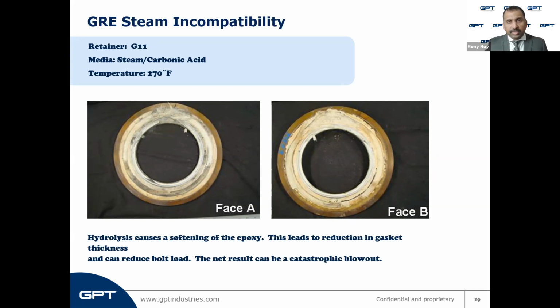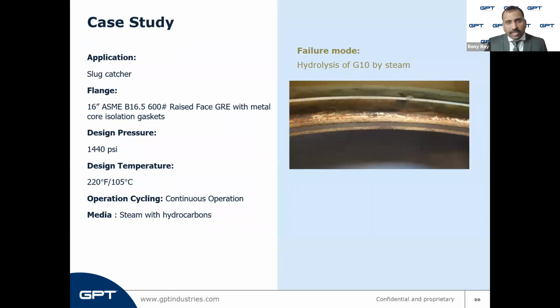And this can be seen from the two images. G11 is rated at 200 degrees Celsius. So the 270 degrees Fahrenheit should not have been a factor, but the softening of the gasket due to the steam introduction and the volume loss led to a blowout, which is a real danger. A case study to prove this point is here.